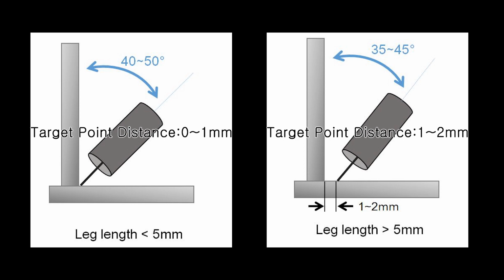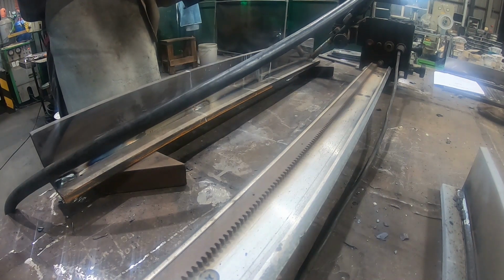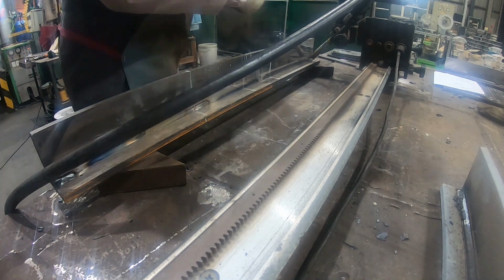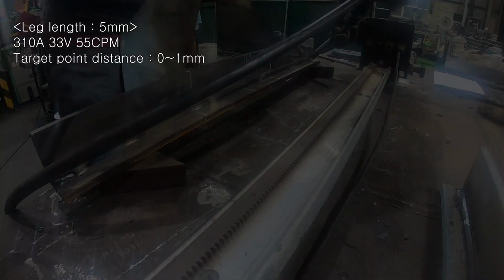If more than 5 mm of leg length is needed, 1 to 2 mm of distance is recommended. In order to secure 5 mm for each leg length, let's proceed with welding with 310 ampere, 33 volts, 55 CPM.